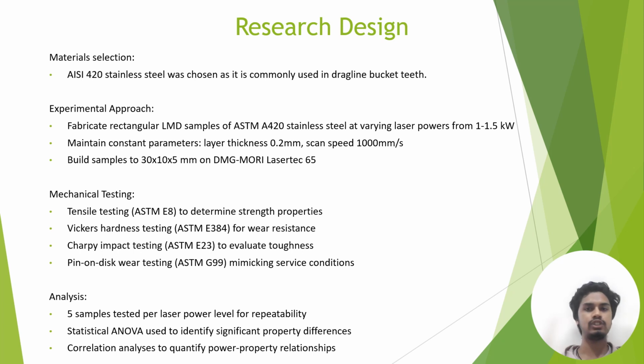E8 using an Instron 5969 universal tester with a 100 kN load cell recording maximum load and elongation. Hardness will be measured using a Vickers indenter under 500 gram load as per ASTM E384. The Charpy impact test complying with ASTM E23 will determine the fracture toughness, and then we'll evaluate the wear as per ASTM G99 using a pin on disc tribometer method.